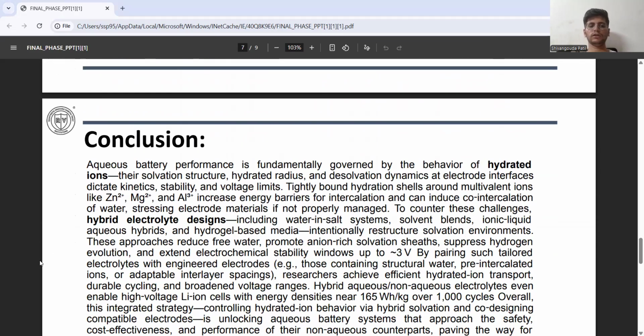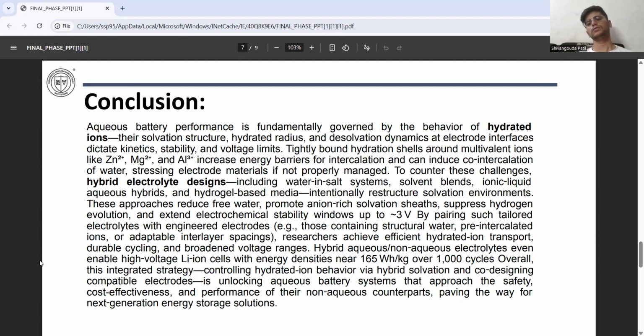So now here we come to the conclusion of this topic. Aqueous battery performance is fundamentally governed by the behavior of hydrated ions. Their solvation structure, hydrated radius, and desolvation dynamics at electrode interfaces dictate kinetics, stability, and voltage limits. Tightly bound hydration shells around multivalent ions like zinc, magnesium, and aluminum increase energy barriers for intercalation and can induce co-intercalation of water, stressing electrode materials if not properly managed.